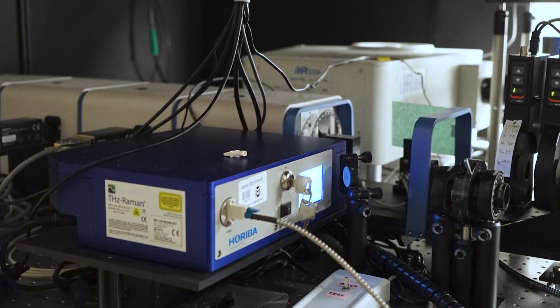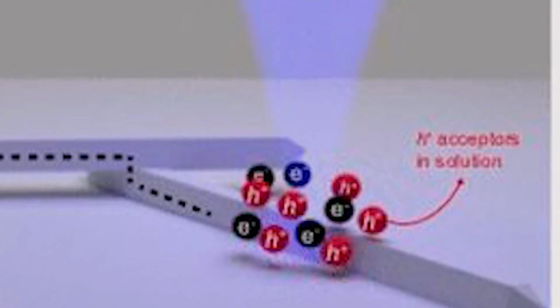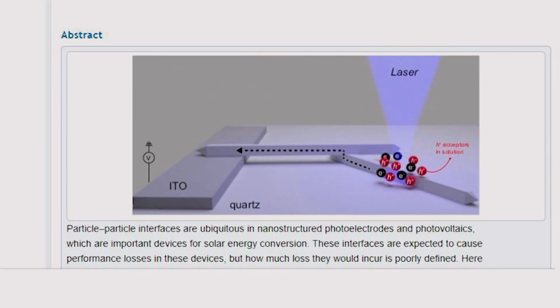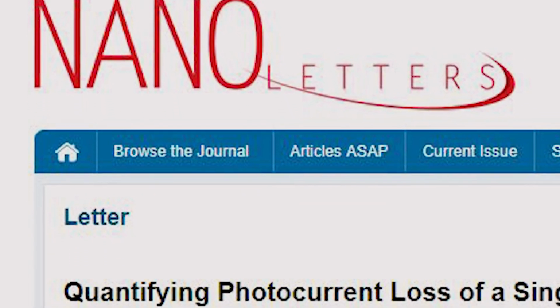So other researchers have used a scanning photocurrent technique to map the energy conversion efficiency of a bulk crystal. We are applying that same method with better optics and a tighter laser focus to study these very ultra-thin, 3-atom thick materials. We raster a laser across a sample, and when the light hits the sample, it generates electrons and charge carriers that we can separate and collect as electricity in our cell. These are the first spatially resolved photoelectrochemical measurements of these 3-atom thick materials.